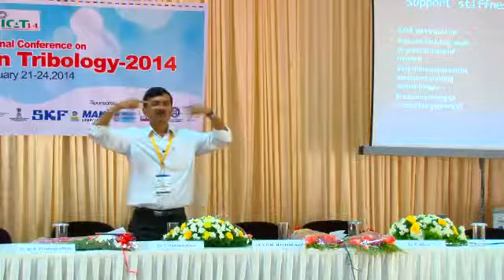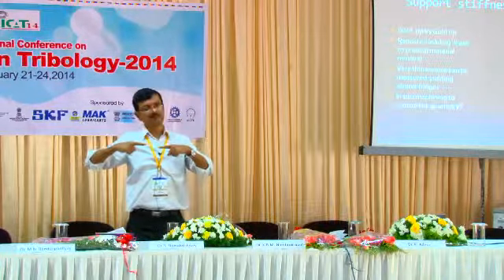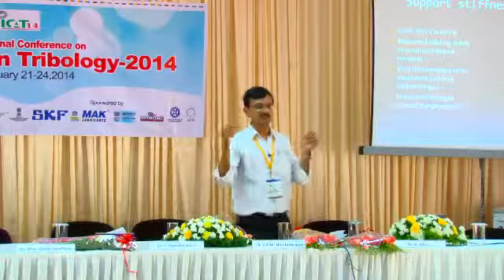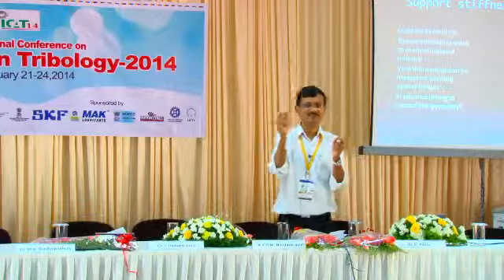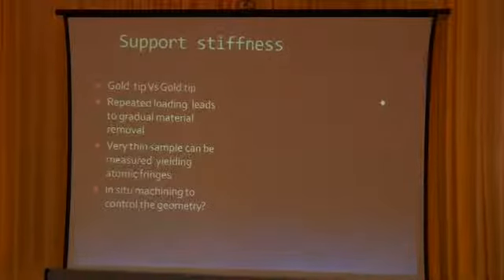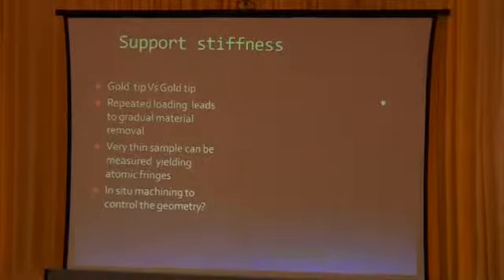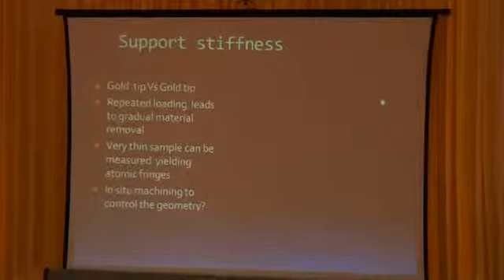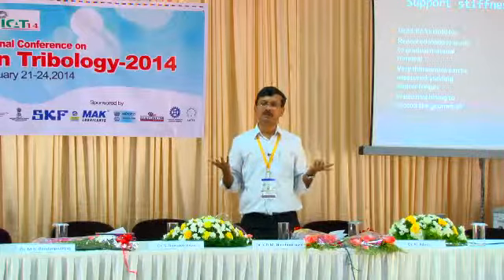What is the experiment? You see this scale is about 50 to 100 nanometers, the tip diameter. You bring two 100 nanometer tips close to each other with one eye closed. You don't have stereoscopic vision in TEM, right? That is more difficult than putting a thread through a needle eye with one eye closed. No stereoscopic vision. We bring it to this, align it and rub it. So you need high stability,